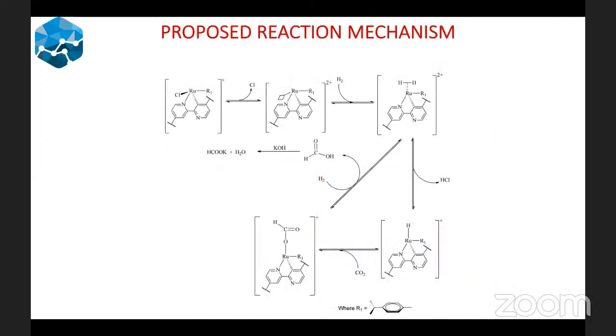Now, let's talk about the reaction mechanism. How are we forming formate from this reaction? If we have our MOF, so if you assume that this is your MOF backbone with your ruthenium 2 center, and of course where your linker is represented by this your pyridylamine. The first step is elimination of your chloride from the ruthenium center. By so doing, it means you generate this open metal site, and of course